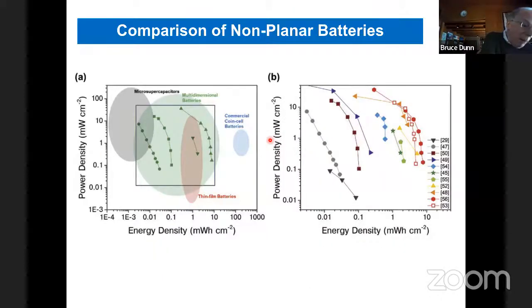So I'm just about winding up with the talk. Let me just give you a quick comparison of where we are with non-planar batteries. This is a Ragone plot, but again, it's per square centimeter because for microbatteries, it's the area that's important. The volume is really not that important in that regard. You can see where micro supercapacitors are. They give you high power, no question about that. You can see where the various multidimensional batteries are and how thin film batteries compare with that. This has been pretty gracious to give them a milliwatt hour per square centimeter, but okay, we'll give them the benefit of the doubt. And you can see that really the multidimensional batteries are up around 10 milliwatt hours per square centimeter. So the field is continuing to advance. We're not there with regard to commercial coin cell batteries, but clearly we are getting close.